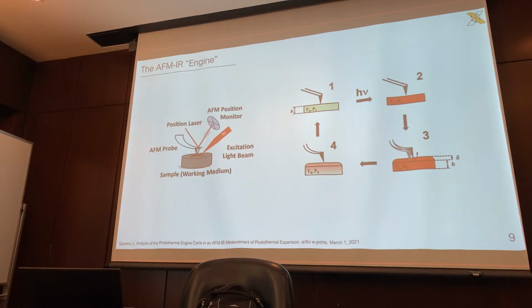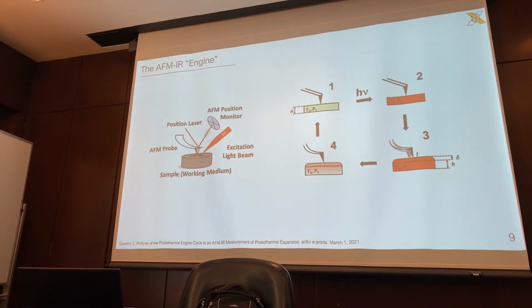Now, the interesting thing is that normally in a conventional engine, we consider the medium to be gaseous. But in our case in AFMIR, the medium is actually a solid, and that will lead to further implications that I'll discuss later. So this is the basic diagram of the AFMIR itself. You have the probe, you have the excitation light beam. Our working medium is solid, as I said before. But to actually detect the deflection, we have a position monitor here, which a laser is guided onto. We essentially have a laser that's guided onto the head of the cantilever probe, reflected off the probe, and onto the position monitor. And this is how we can detect deflections on the order of picometers.